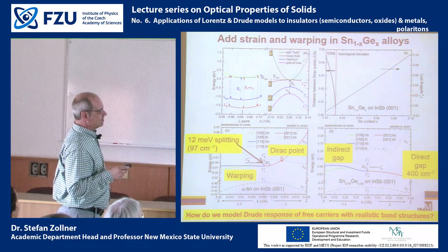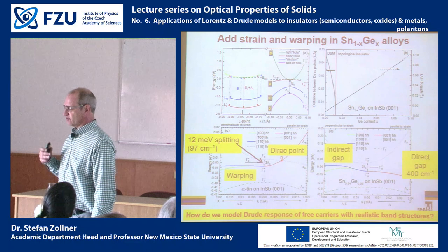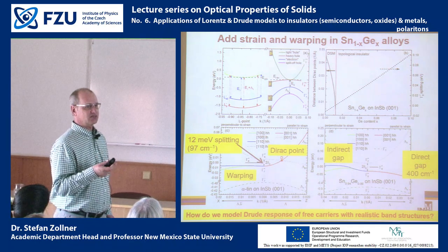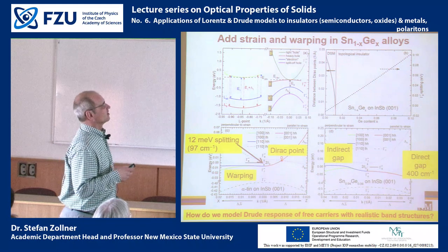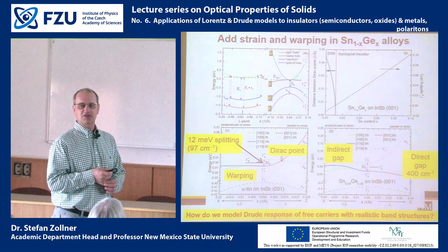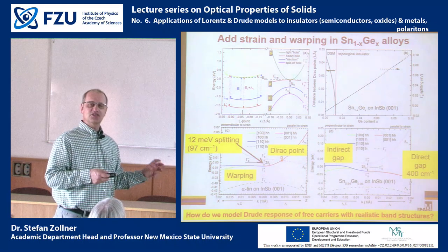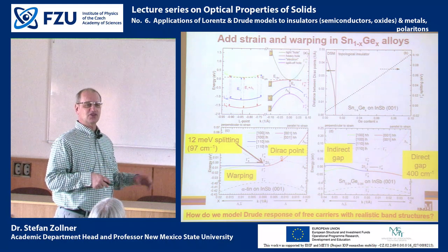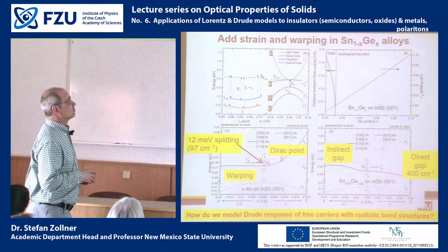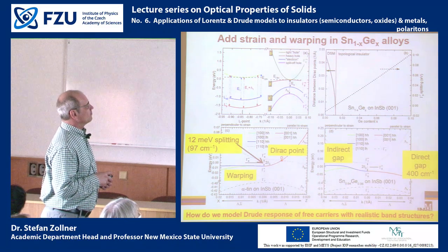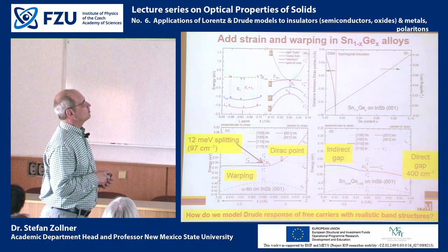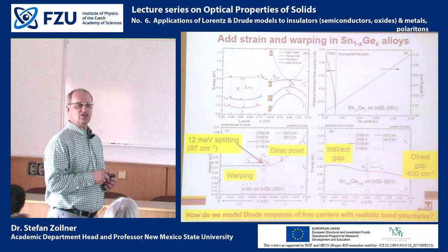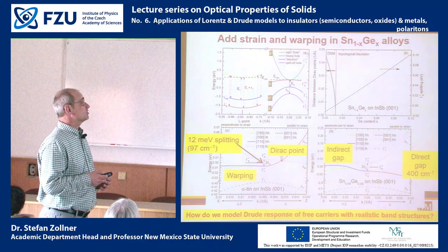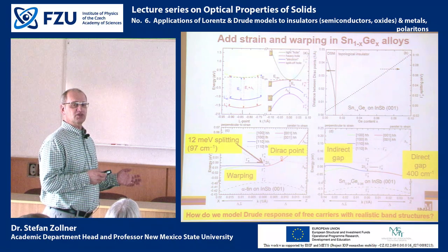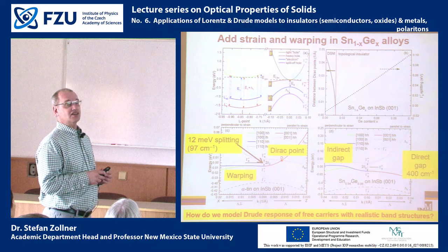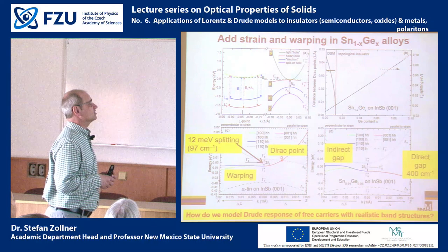The problem with alpha tin is that alpha tin is the gray tin, that's the cubic tin. It converts into white tin, which is hexagonal, at 13 degrees Celsius. So it is very difficult to do experiments with alpha tin because you constantly need to grow it, you need to produce the material below room temperature, and you need to do your experiments with it below room temperature. That's very hard. But if you grow alpha tin as an epitaxial layer on a cubic substrate with a thickness of, say, 1,000 angstroms, then the cubic substrate stabilizes the alpha tin, and that means that you can do experiments with alpha tin at room temperature.